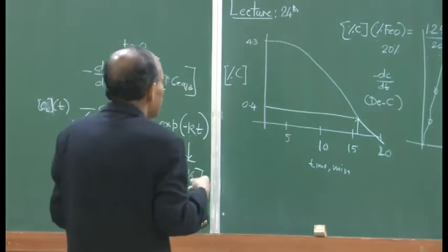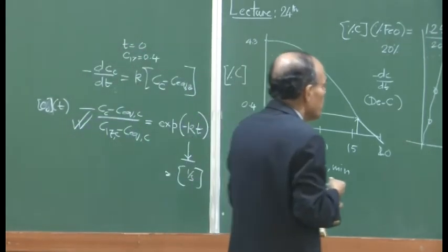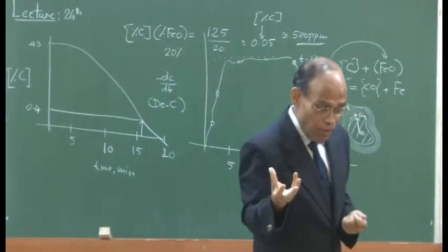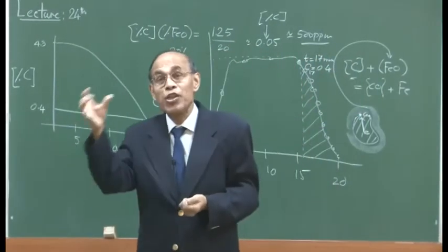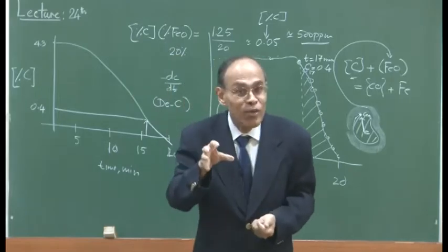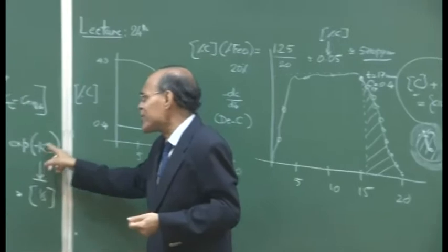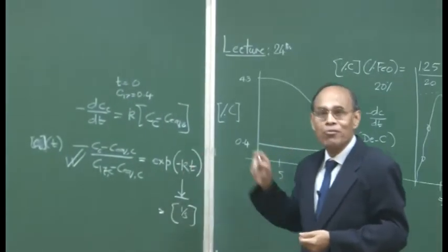So, the vessel geometry etc. And maybe the wear and tear of the lance tip. Rate constant determined with a new lance and rate constant determined with an old lance may not be the same because of the wear and tear of the process. So, as such there is going to be some uncertainty in the measurements of K.